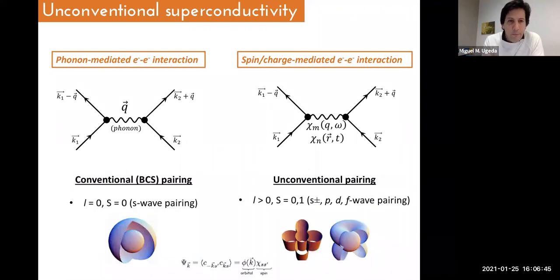So the phonon-mediated Cooper pair formation is well described by the BCS pairing, the Bardeen-Cooper-Schrieffer pairing, and the wave function of the Cooper pair is in general isotropic, constant in space. In the case of unconventional superconductivity, which refers to everything else that is not phonon-mediated, the symmetry of the system is lower, the Cooper pair wave function is lower, and therefore this leads to more anisotropic order parameters, right? In this case, the spin of the Cooper pair has to be in general a singlet, whereas here it can be either a singlet or a triplet component.